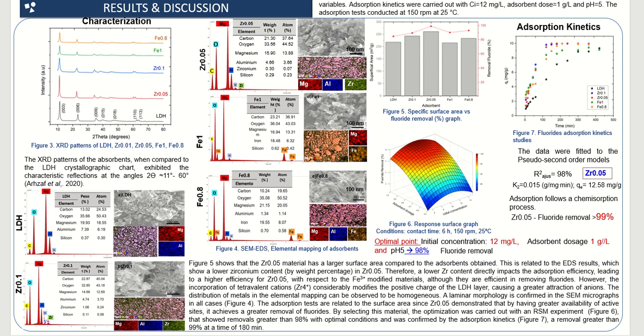99% removal was obtained. They were evaluated by mathematical models to know the nature of the process, and the data were adjusted by the pseudo-second order model, where possibly a chemisorption follows and that the adsorption.